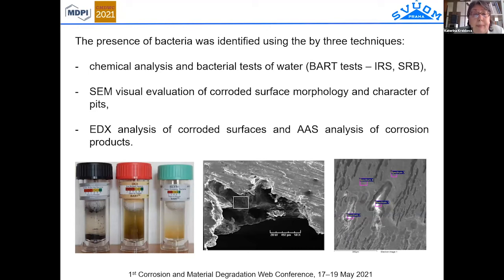How can we identify the presence of bacteria in the system? We use three basic approaches. The first is that we look at the water which is in the pipelines or another system, which means we perform basic chemical analysis, looking for sulfate and other species, and also basic bacterial tests to identify the presence of iron or sulfate reducing bacteria. We also look at the corroded surface, the morphology of the surface, the character of the pits, and perform detailed analysis of the corroded surface to identify a higher amount of sulfur or of other species.